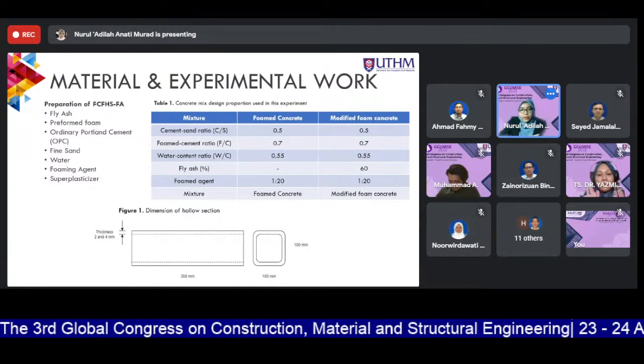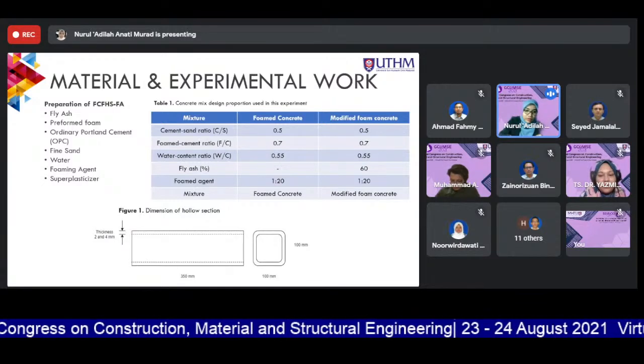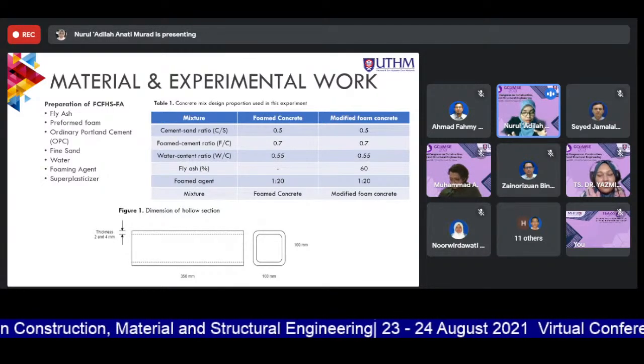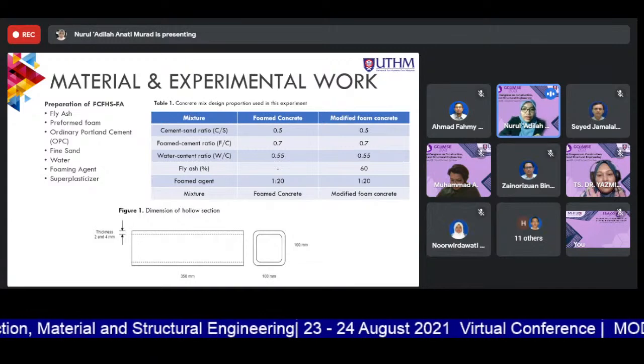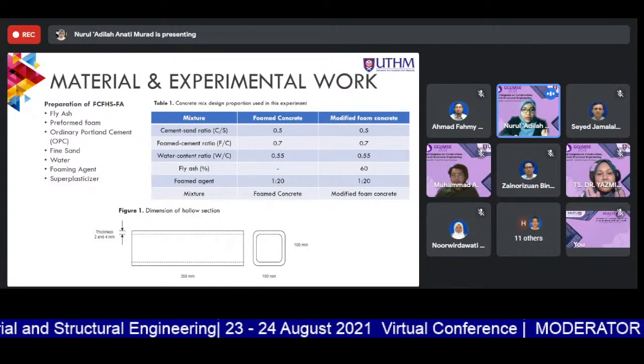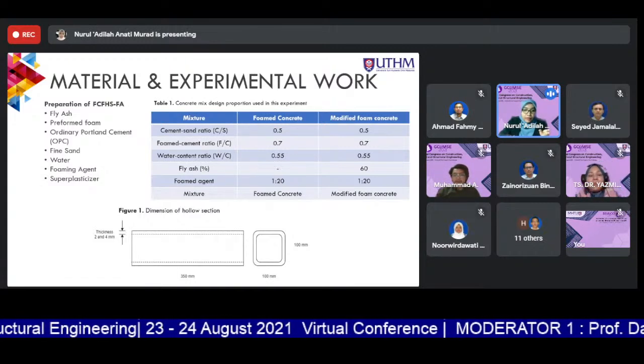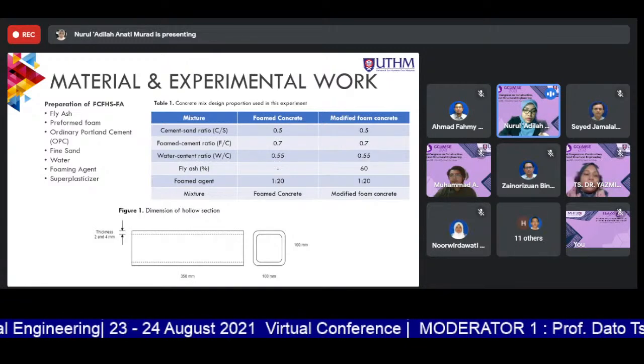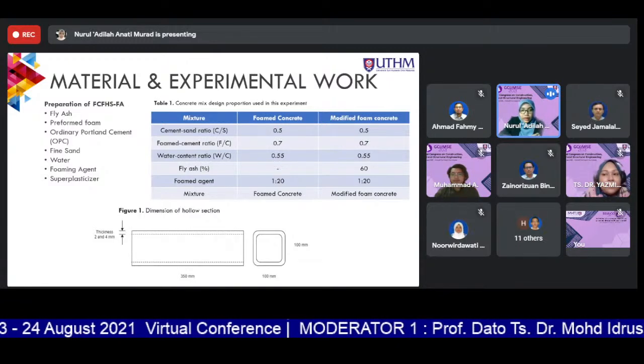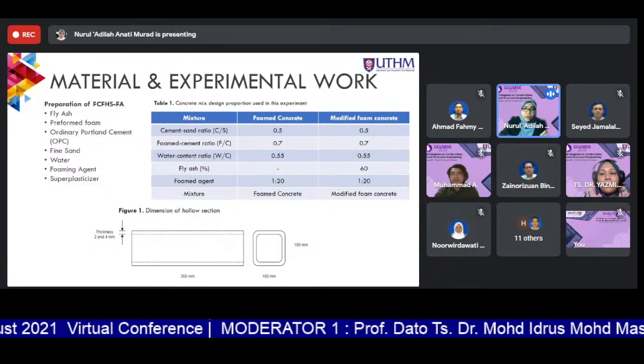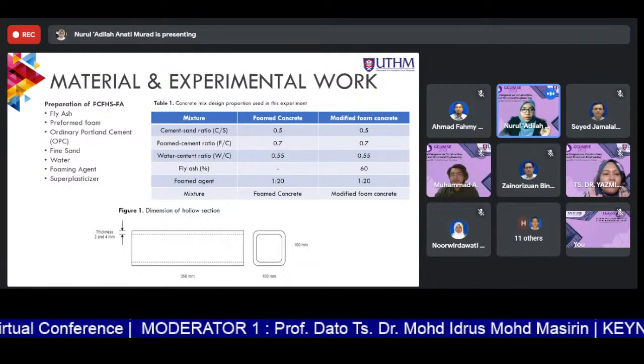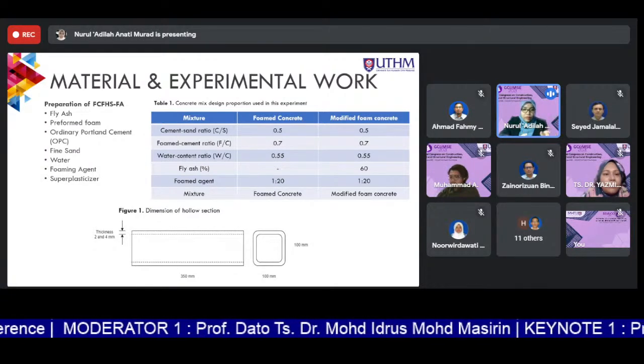And this figure below is the dimension of the hollow section used, which is the square hollow section, with a length of 350 millimeter and dimension of 100 by 100 millimeter. And this experiment has used two different thicknesses, which are 2 millimeter and 4 millimeter.